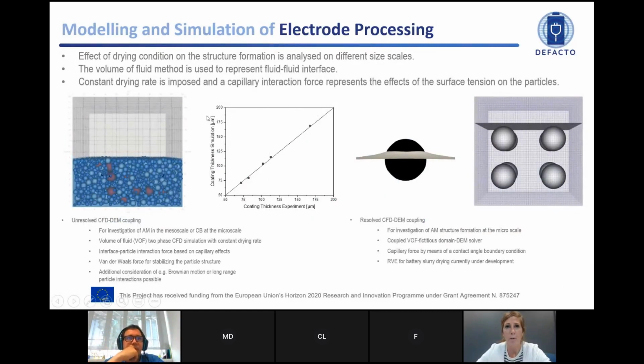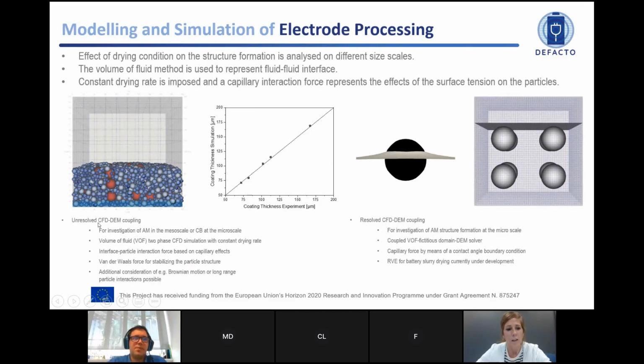Then once we have this carbon black agglomerates size distribution fixed, we intend to go to the drying conditions, and here what we aim to do is study properly the effect of this drying condition on the structure formation. For this, we need to rely on two different size scales. One is the unresolved CFD-DEM coupling, and the other one is the resolved CFD-DEM coupling. Talking about the unresolved CFD-DEM, we aim to investigate the active material in the mesoscale or the carbon black at the microscales. From the results, what we can say is that the simulation results are comparable to the experimental results, and it can be seen here.